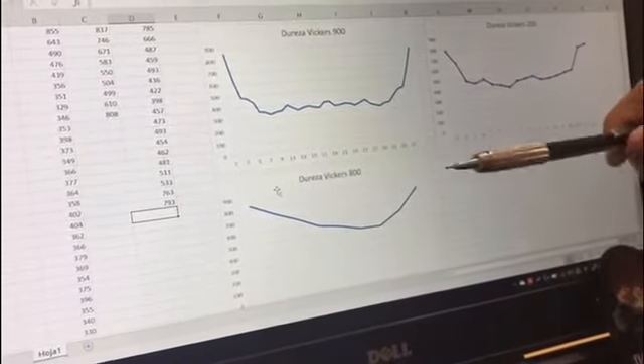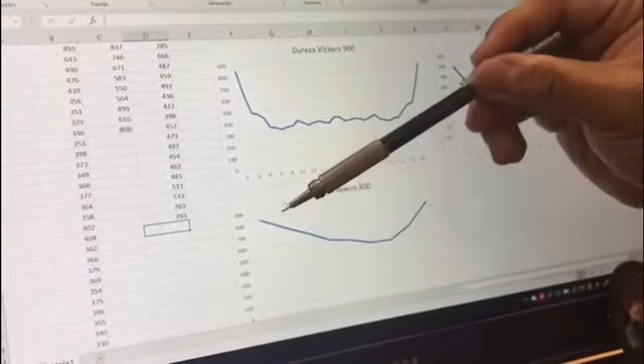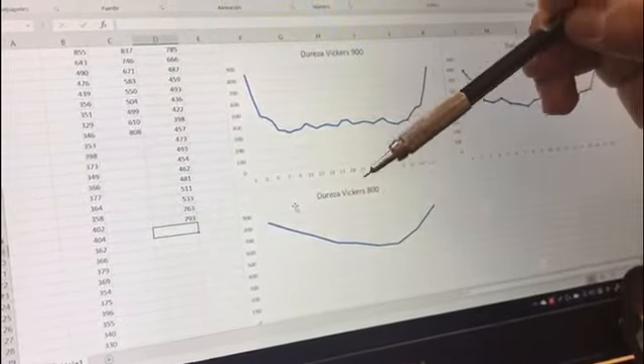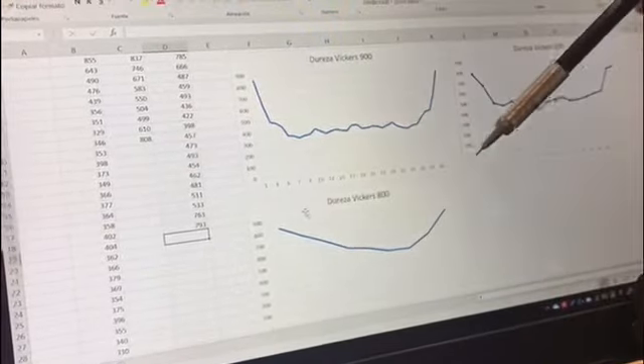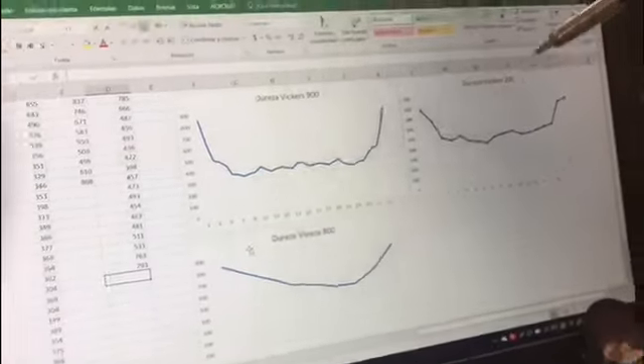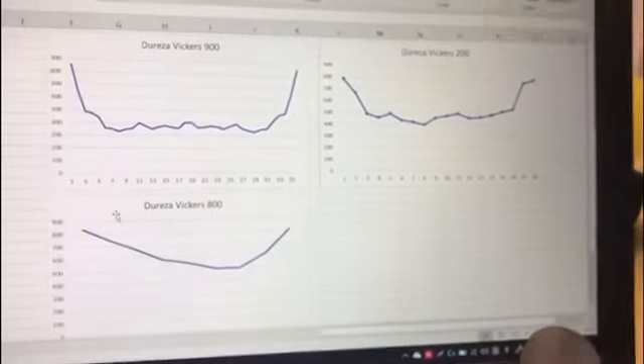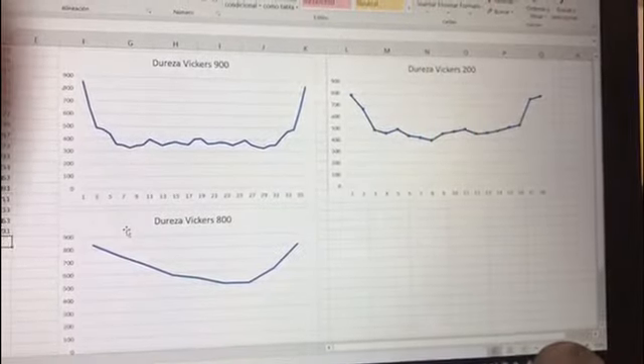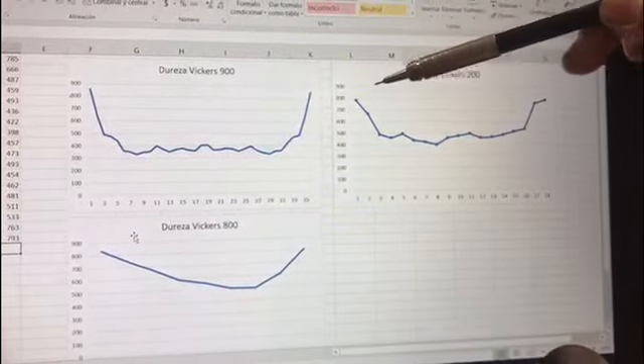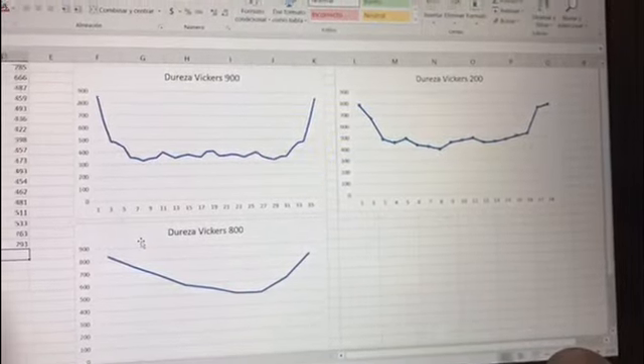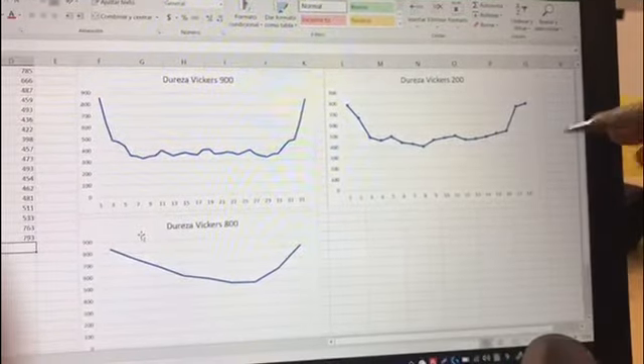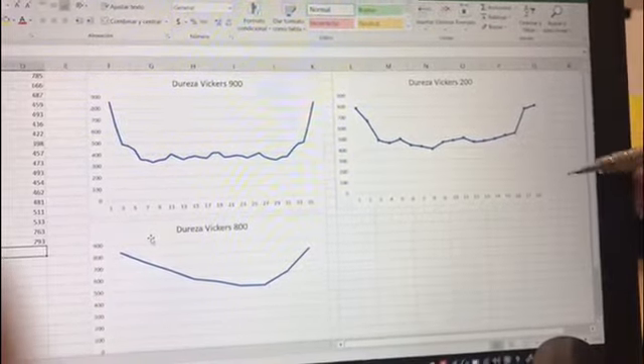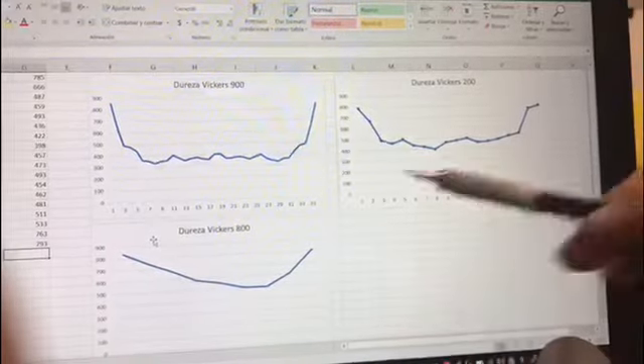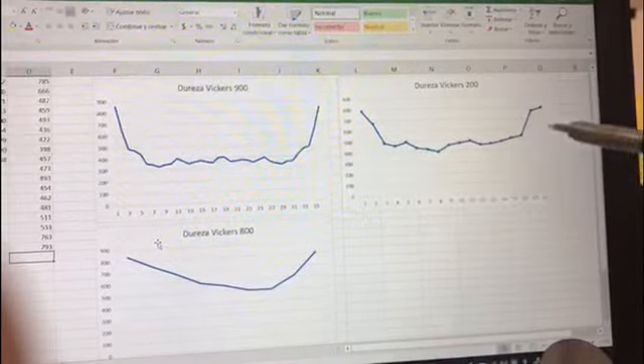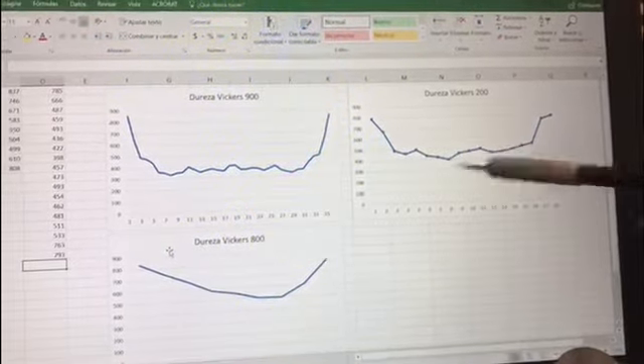Continuing with the second heat treatment, we found almost the same behavior. Unfortunately, we couldn't do more indentations, but we found that it's the same behavior. And in the last one, which is the third heat treatment, the hardest one, luckily we found the same behavior as the one at 900, and we see that this heat treatment was way better than the 900 because the material overall had better properties than the other two.